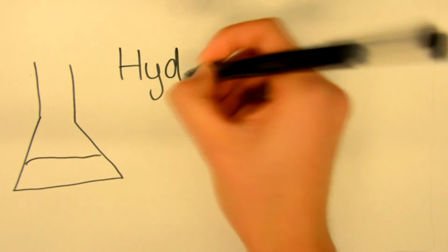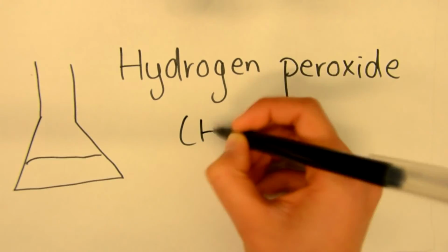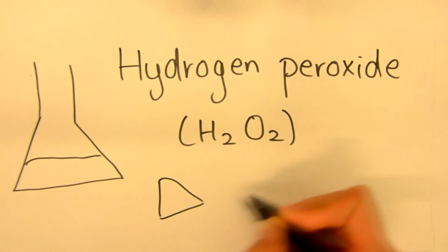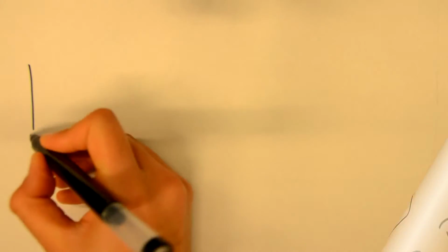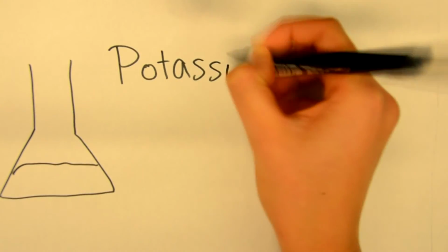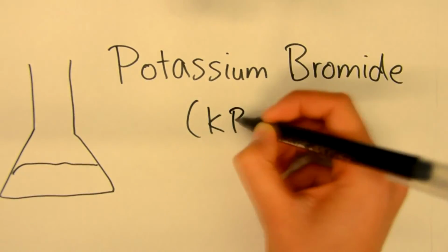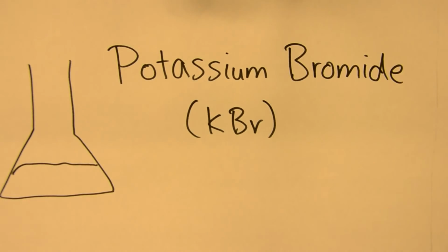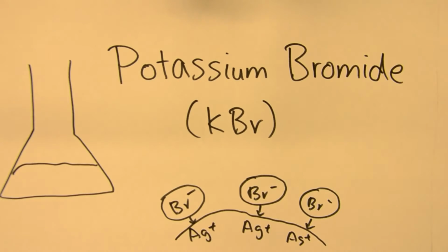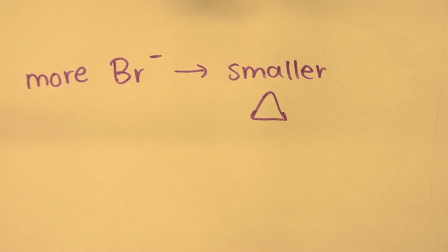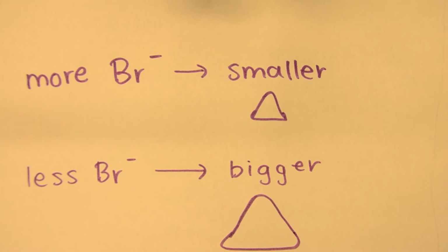You also need hydrogen peroxide, which oxidizes solid silver back to silver ions, preventing the uncontrolled growth of nanoparticles and etching nanoparticles into nanoprism shapes. Finally, potassium bromide is needed, which controls the size of nanoparticles. It does this by binding strongly to the silver surface, forming silver bromide, which arrests growth of the silver particle surfaces. The more of it you have, the smaller the nanoparticles become.